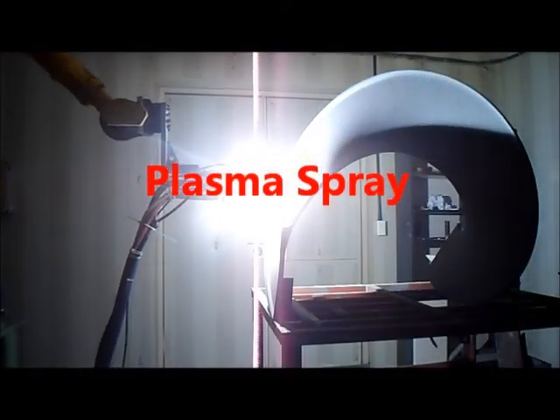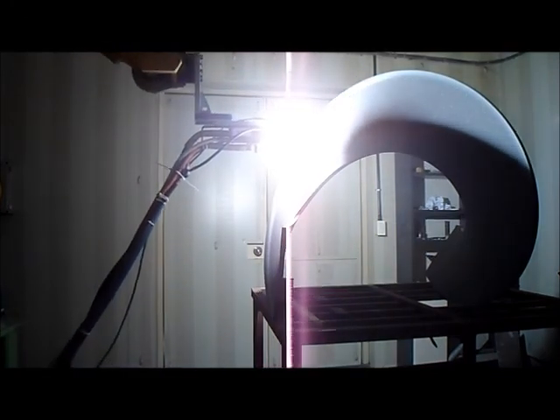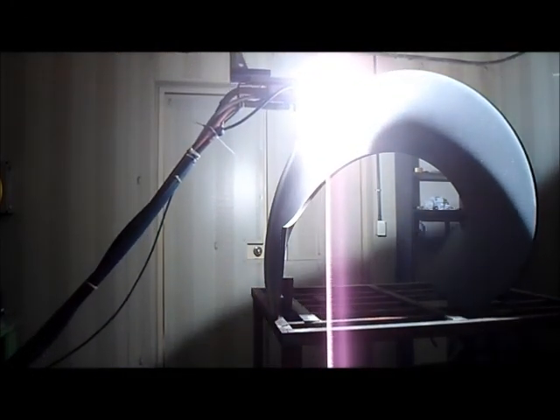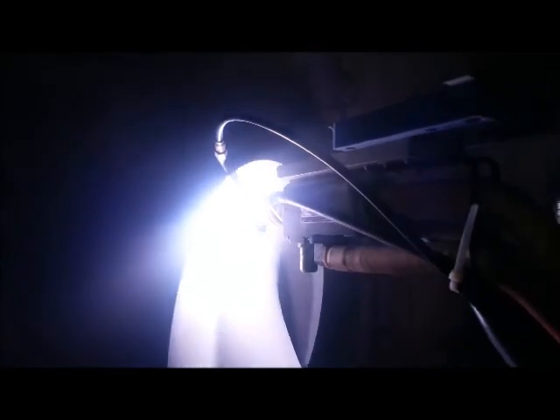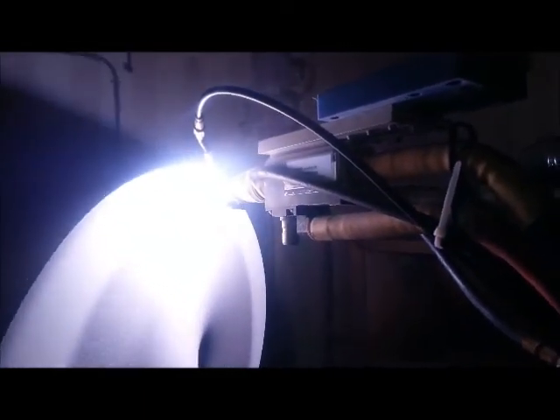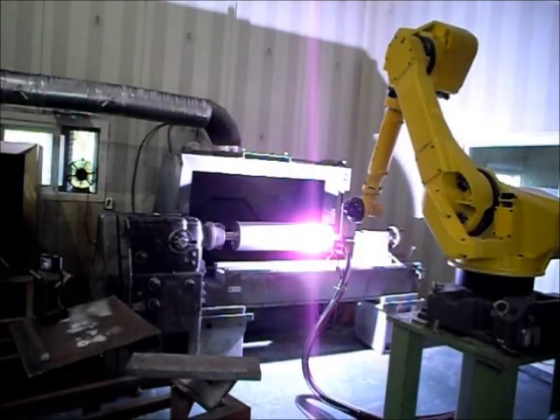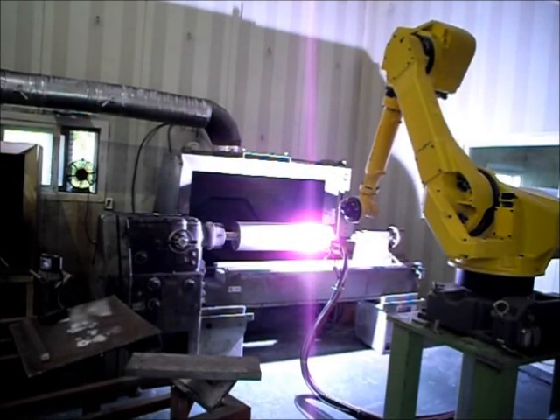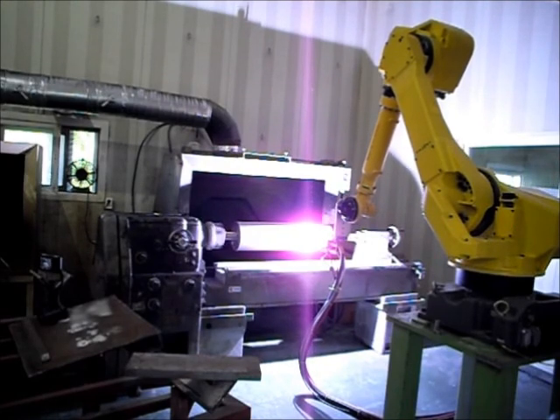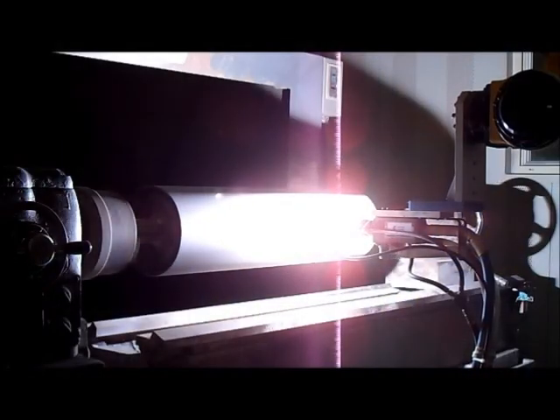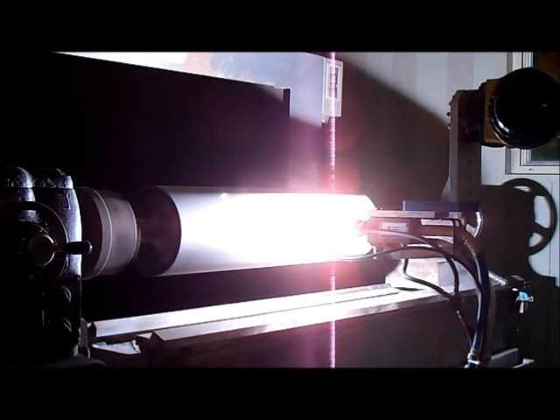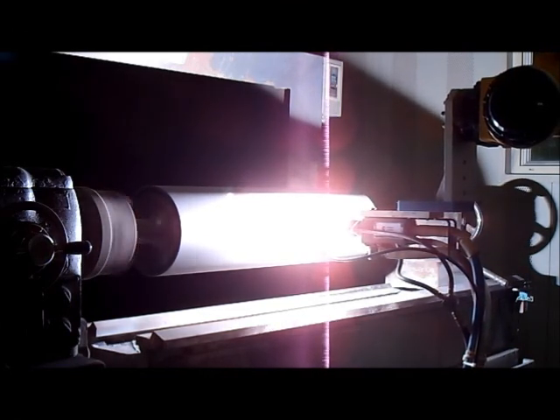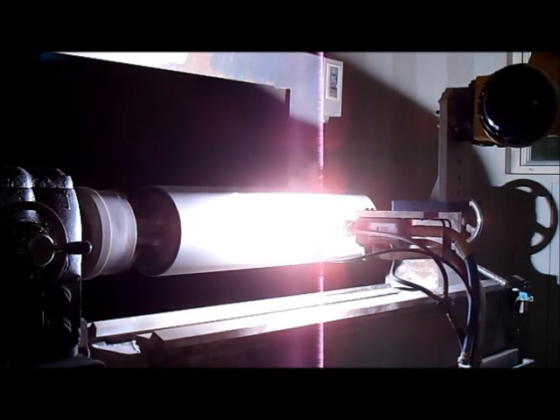Plasma spray. The plasma gun introduces inert gas and lets it pass through the arc stream of the nozzle. The inert gas grows to a high temperature plasma stream and coating powder is dropped into the plasma stream and is melted, and the melted powder wrapped by plasma flies to the targeted surface. The plasma flame is small with high temperature, about 10,000 degrees Celsius. A plasma flame can melt high temperature materials like ceramics and transfers less thermal effect to the base materials by the small heat capacity.